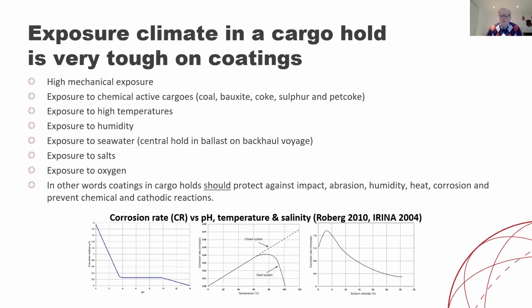The exposure climate in a cargo hold is very tough on coatings. As already mentioned by the earlier panelists, you have high mechanical exposure. You have exposure to chemically active cargoes, you have high temperatures, humidity, seawater, salts, and of course, exposure to oxygen. All of this creates both mechanical damage and corrosion. So in other words, the coating in a cargo hold should protect against impact, abrasion, humidity, heat, and prevent chemical and cathodic reactions.